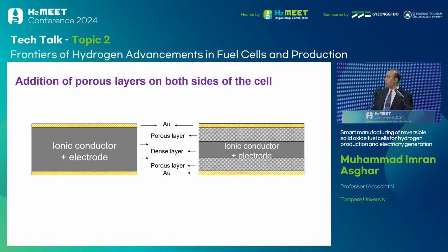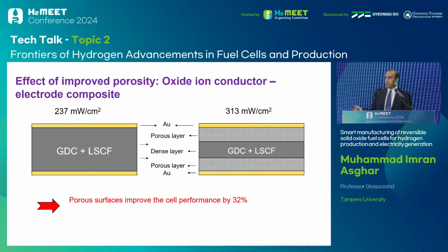To overcome them, we fabricate our cells with different structures. We fabricate the single layer cells and we add some porous layers on both sides of the cell to improve the surface area. And what we found is that when we add this surface area, the performance improved by 32% for oxide conductors. The porous layers consist of the same material, but they have better porosity. So we get this improvement of about 32% enhancement in the performance.